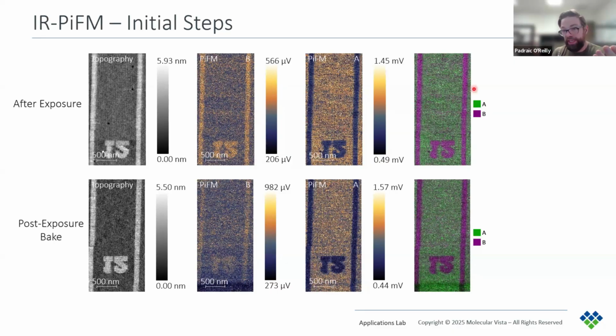And finally, we can overlay these two wave numbers and show that wave number A is brighter where B is darker and vice versa. Okay, so now that we have these good wave numbers for the exposed and unexposed regions, we can zoom into the much smaller lines in between these two larger lines here.